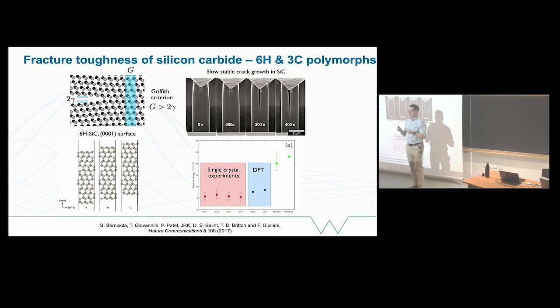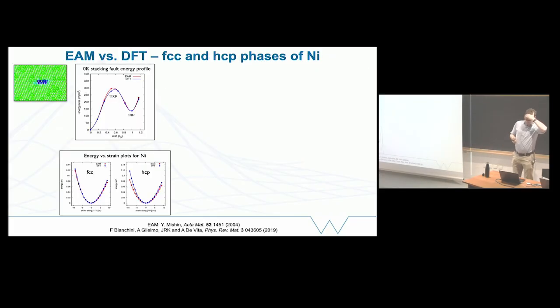But if we're interested in mechanisms or in kinetics, it's much more challenging, and that's where I think we really benefit from potentials. I promised I would return to this example of the superalloy. We have these two partial dislocations jiggling around, and we wanted to understand whether we can get this stacking fault separation distance right. That's the experimental quantity that we'd like to get access to in this case.